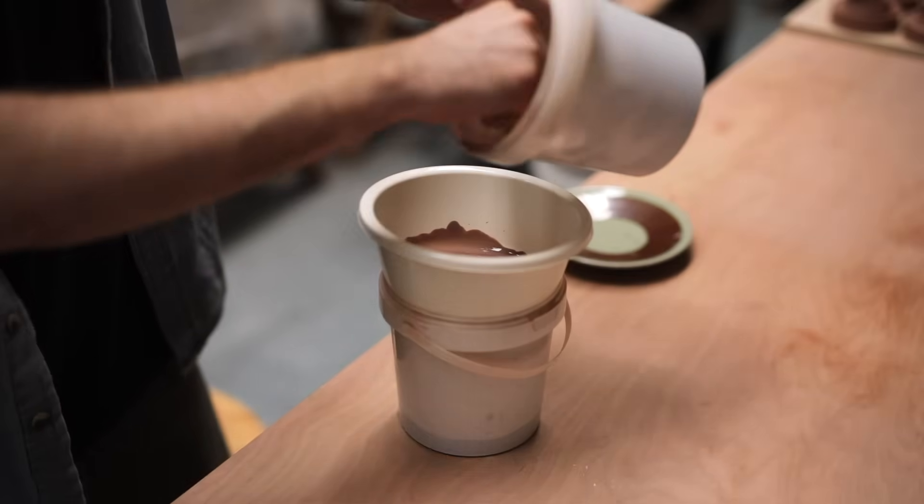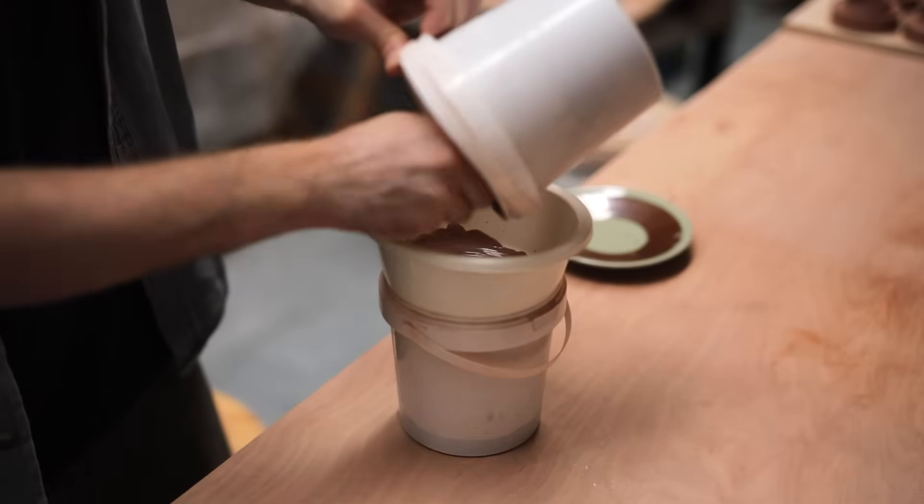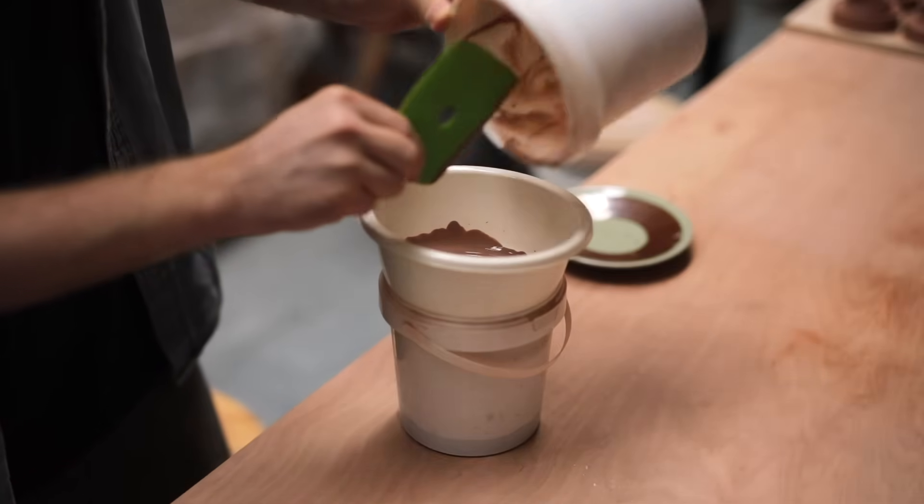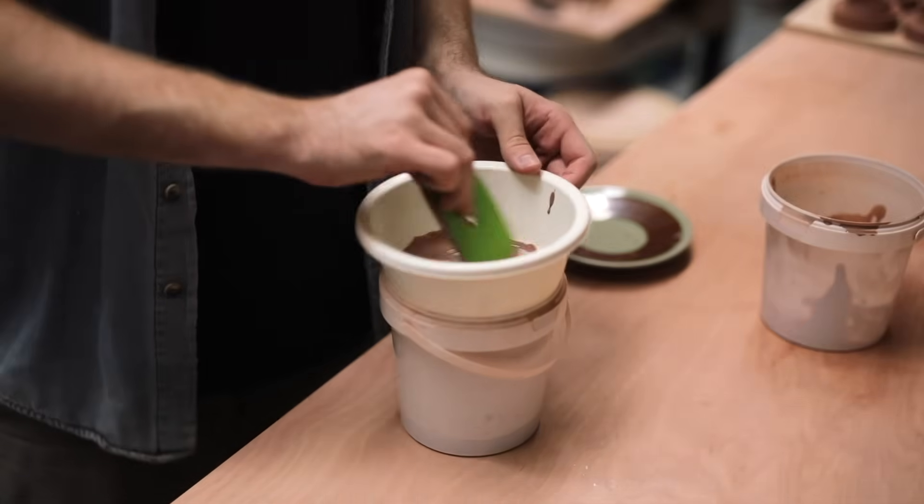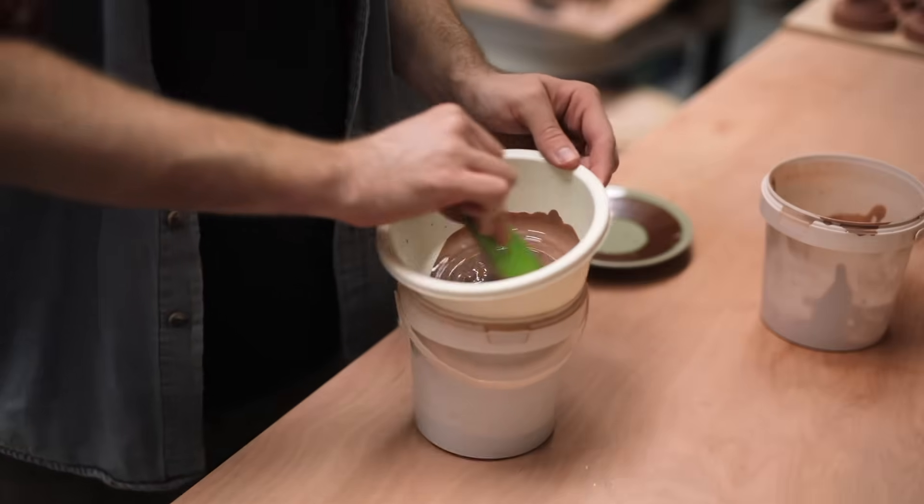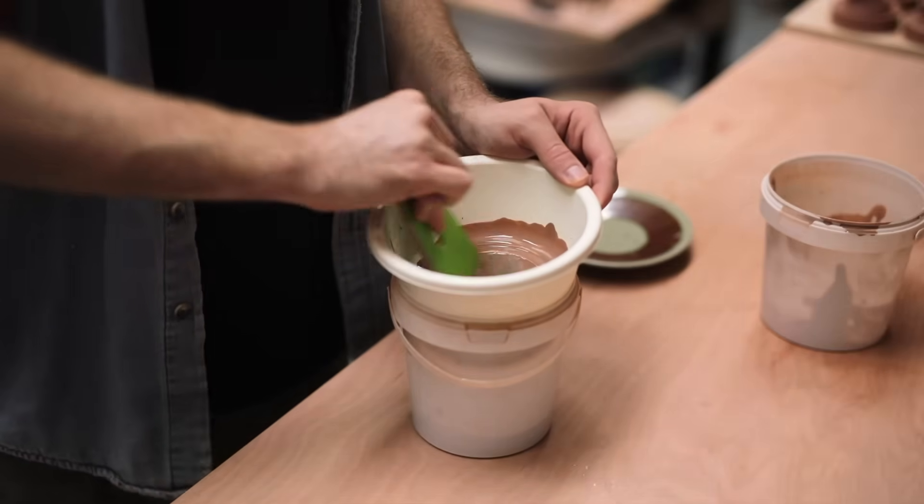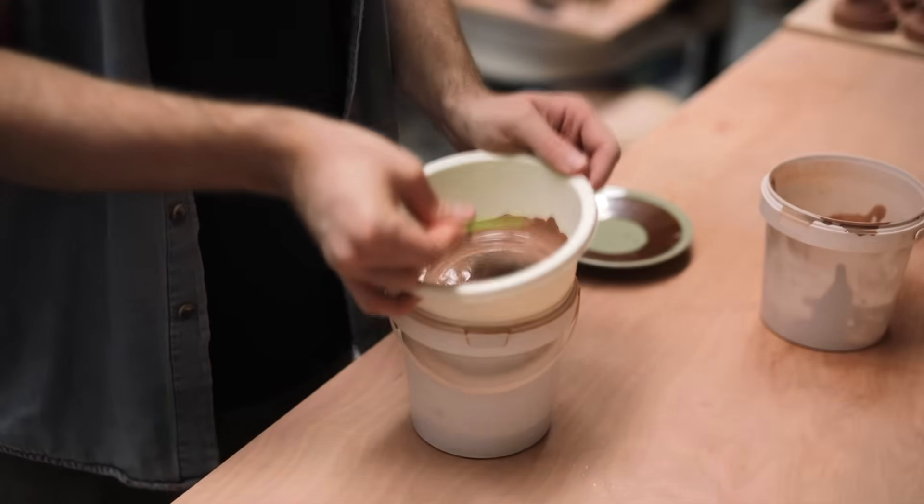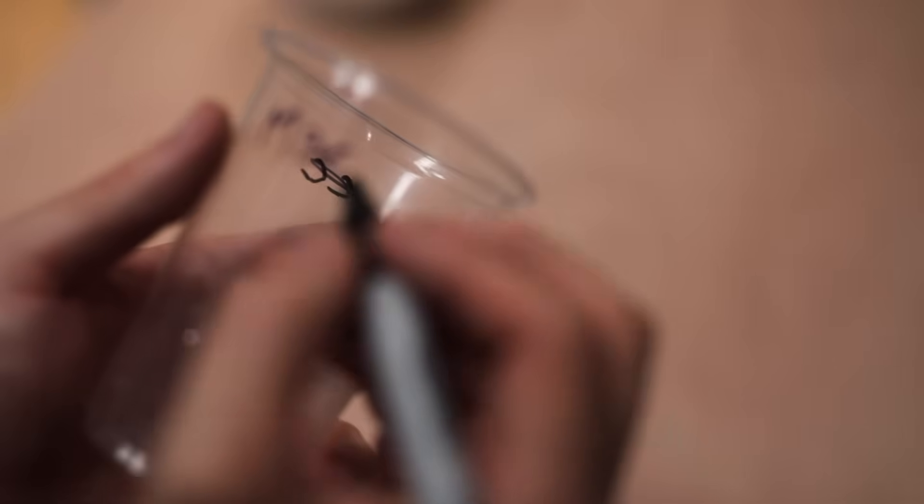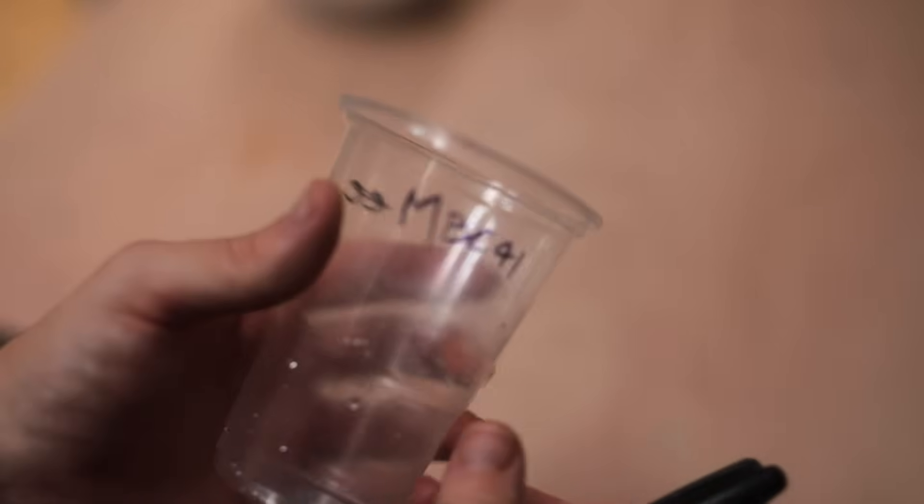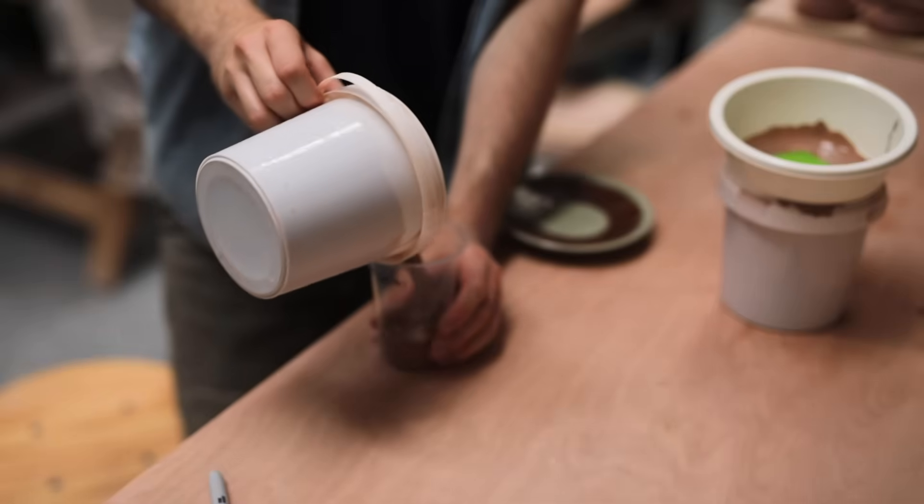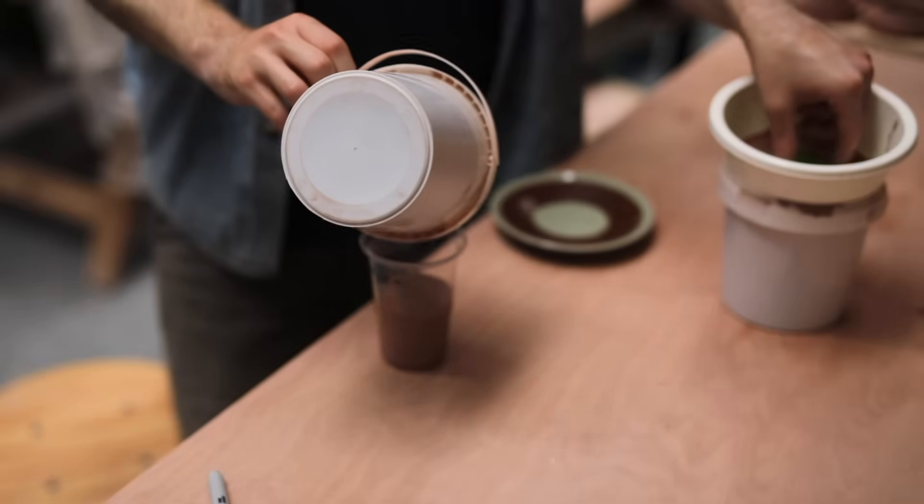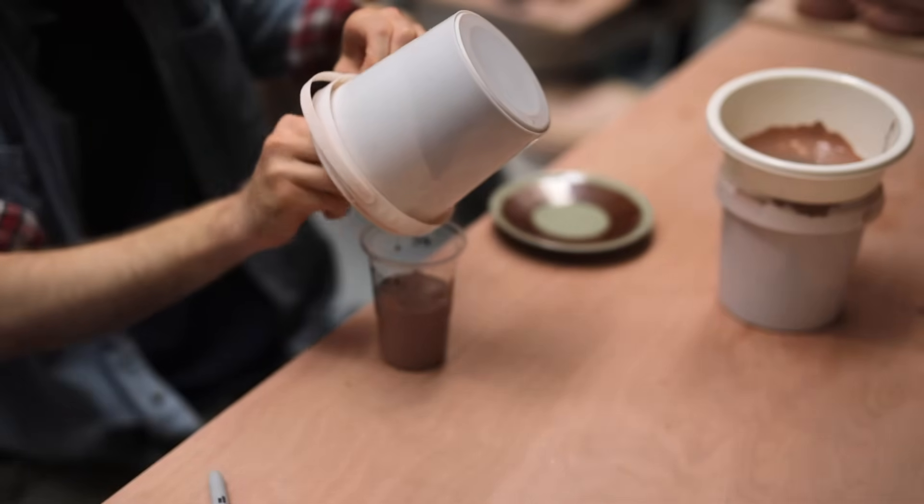I'll then sieve this mixture, and generally in terms of consistency, I try to make the mixed up glaze about the same consistency as double cream, or if I were to dip a finger into it, I would want the glaze to coat it, instead of it just flowing off. You'll find that some recipes online also give you the amount of water that needs to be added to the raw ingredients. But, if you're mixing up custom glazes, it's often just a matter of trial and error.